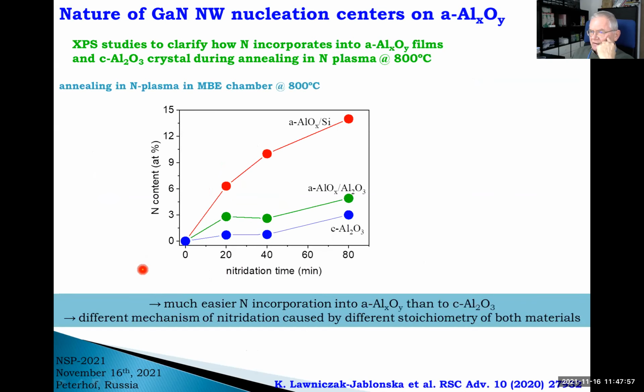To answer this question, we have done XPS studies. The experiment was such that we first annealed our substrates in an MBE chamber in ammonia or nitrogen plasma flow at high temperature, just to simulate more or less MBE growth conditions. And then we studied the samples to see how much nitrogen got incorporated into these films. And you see the results here. Crystalline sapphire was used as a reference, and these are two cases for amorphous aluminum oxide films. For both of them, incorporation of nitrogen into the film is much, much easier than into crystalline sapphire.